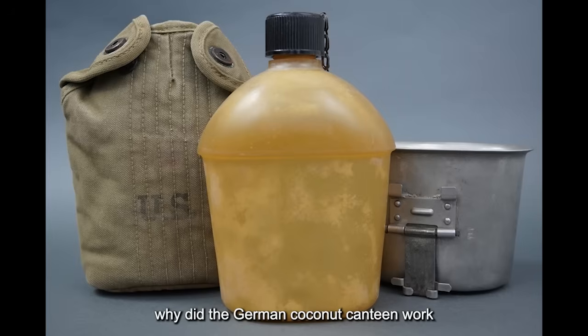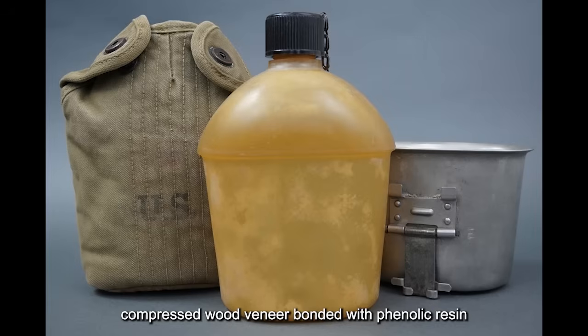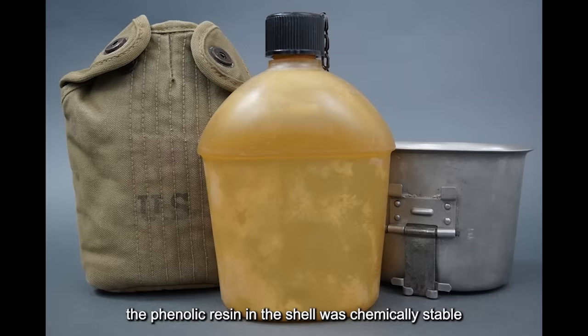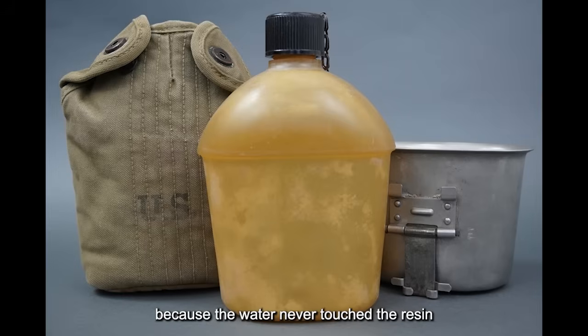Why did the German Durofol canteen work when the American Ethocel canteen failed? Practical compromise over technological ambition. The Germans didn't try to eliminate metal from the water reservoir. They recognized that aluminum was the proven, safe material for containing drinking water. Their innovation was replacing the felt covering, the part that didn't need to be metal, with a superior composite material. The Durofol shell, compressed wood veneer bonded with phenolic resin, provided protection and insulation. The phenolic resin in the shell was chemically stable and thermally cured, with polymer chains cross-linked into a rigid, non-reactive structure. But none of that mattered for water safety because the water never touched the resin.